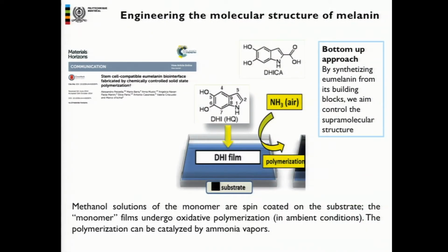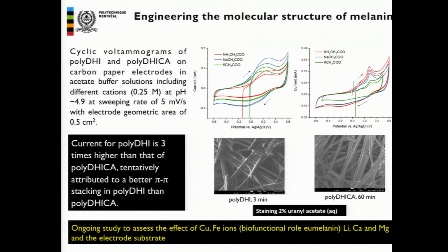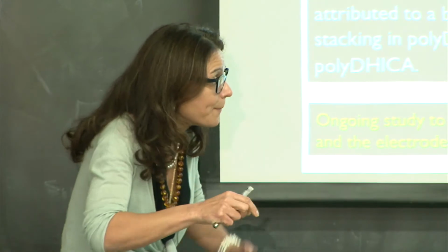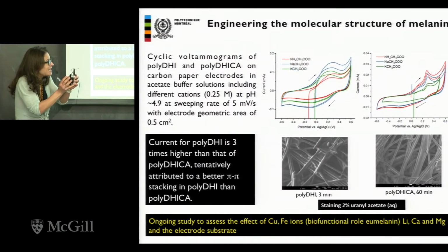So we work with excellent groups, excellent synthetic chemist groups. They give us the monomers, and then we fabricate the film ourselves, so the polymerization happens in ambient condition, sometimes catalyzed by the presence of ammonia. And so we do the engineering of the thin films, and the thin film is really the core of our device. Here we see the effect if we engineer the film, and for instance, we start with the non-carboxylated monomer, where the order is more developed than when we have the carboxylated group adding space during the self-assembly.